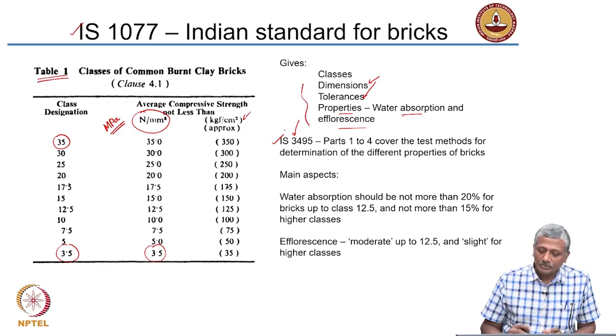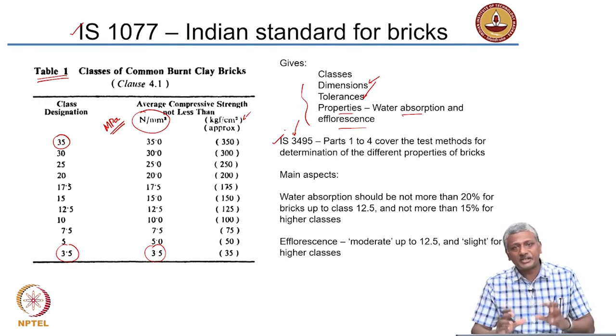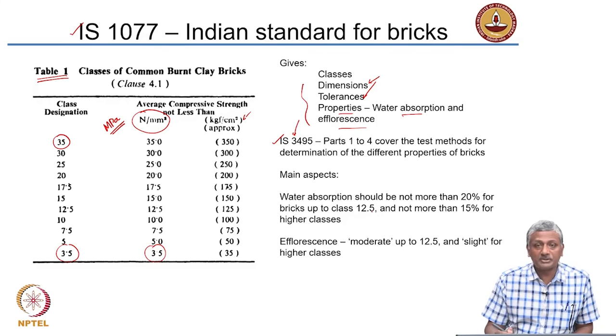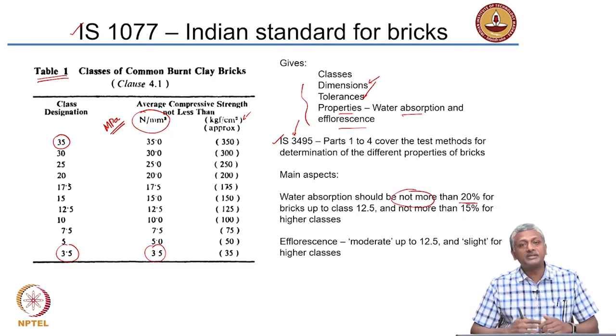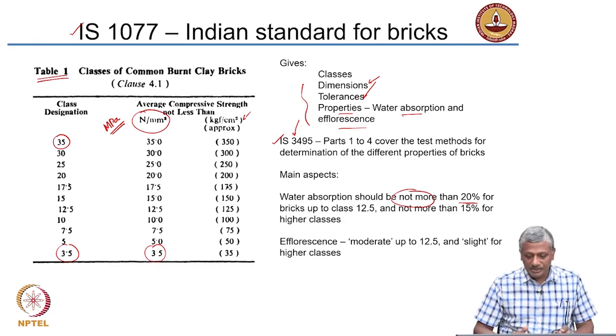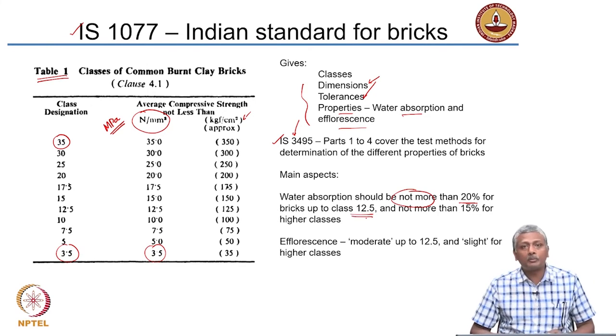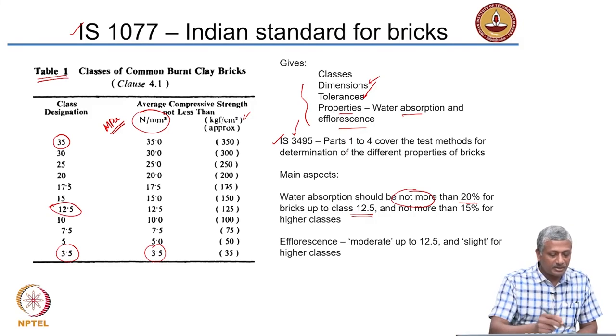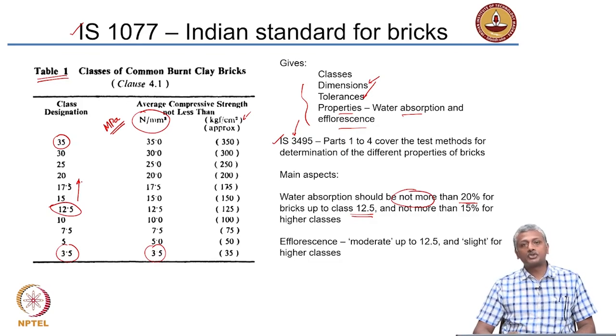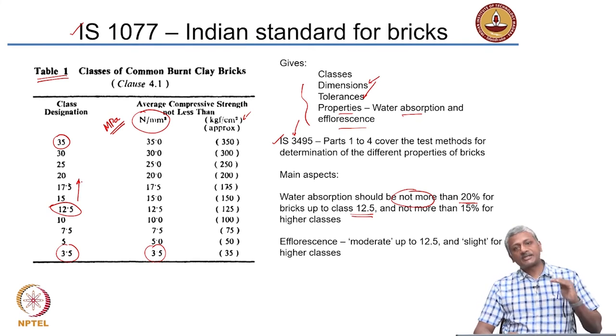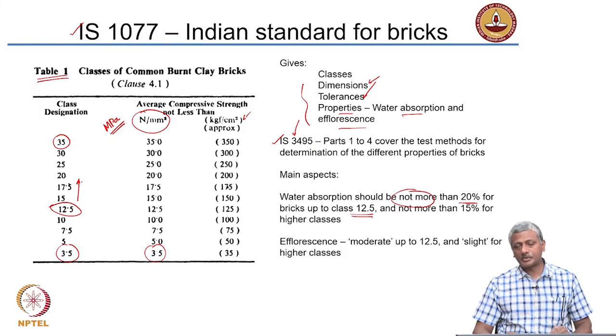Okay. Now, just to condense the main aspects of the standards, I should say that the water absorption in bricks is supposed to be less than 20%, or they say not more than 20%. That means they should be less than or equal to 20% for bricks up to class 12.5, right, up to this class here. And above this strength class, the water absorption should not be more than 15%. Okay? So, you need to select your bricks and brick materials carefully. So, not only does it satisfy the strength requirement, it also has to satisfy the water absorption requirement.